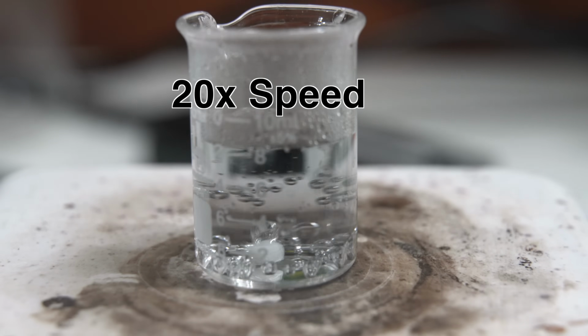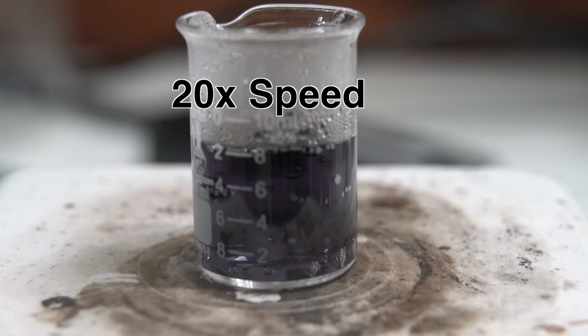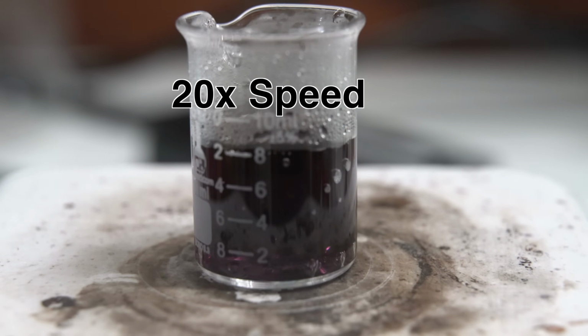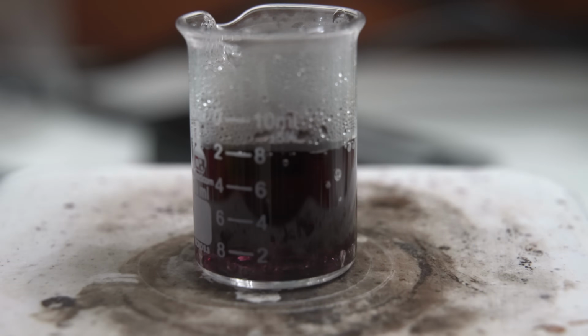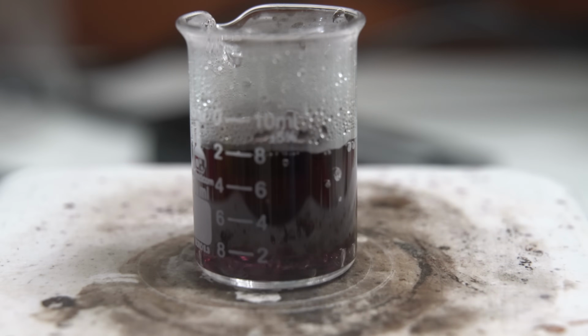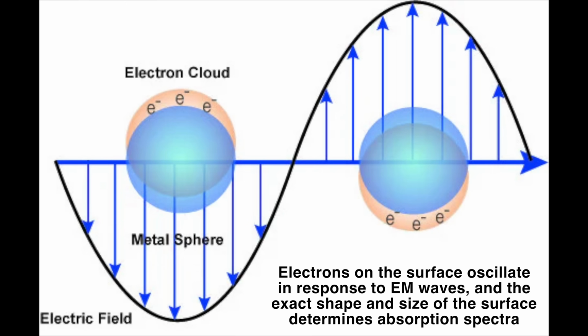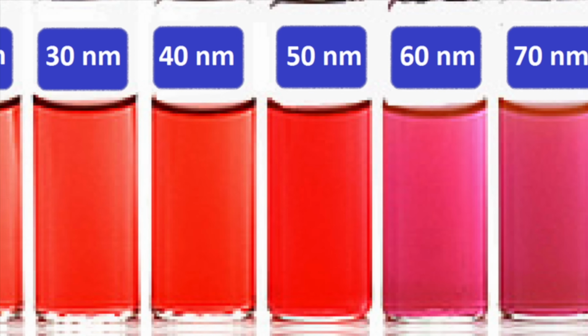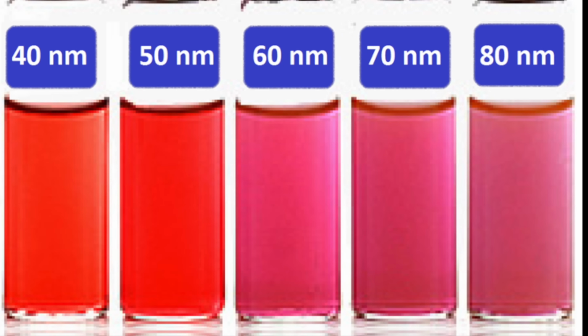In only a couple of minutes, the solution starts to change from clear all the way to a deep purple or red, indicating that we've produced gold nanoparticles. Now, you may be wondering, why isn't the solution gold colored? Well, the reason for the red color is due to a property called surface plasmon resonance. Basically, the shape and size of the gold particles cause light of certain wavelengths to be strongly absorbed. You can even use the color to estimate the size of the nanoparticles themselves.